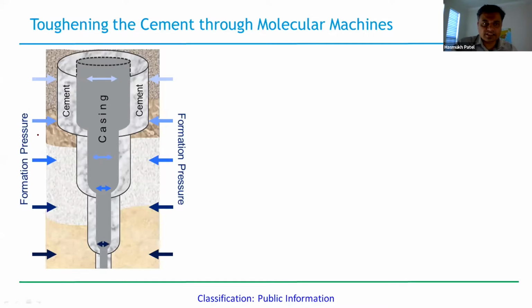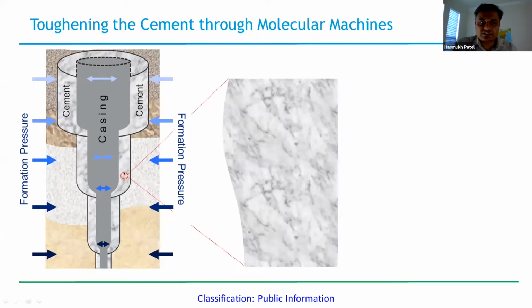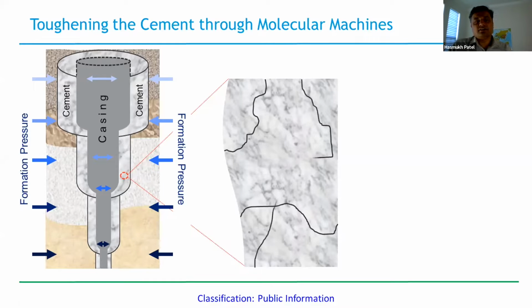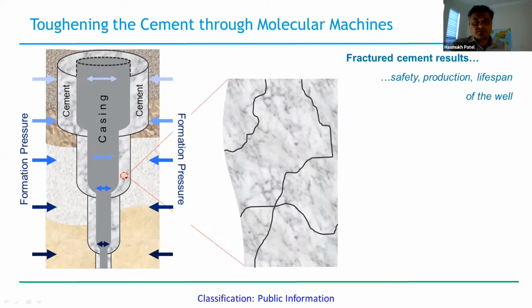What is happening in the casing, this is the production zone, when the oil and gas is coming through the casing. There is a pressure difference between the formation and inside the casing, and that generates uneven stress onto the cement matrix, and those uneven stresses fracture the cement. And if we have fractured cement in an oil well, it's a serious problem. It means we are compromising the safety. It reduces the production of oil and gas, and eventually it will reduce the lifespan of the oil well.